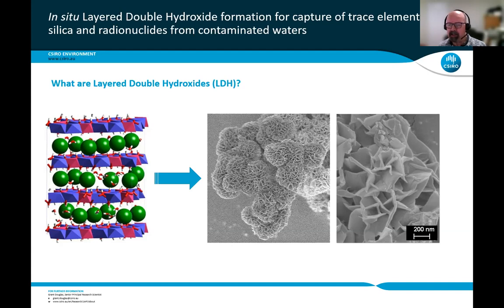Now, you've got a typical basal spacing in a layered double hydroxide between about 1 and 1.5 nanometers. So you're probably looking then at around about, say, 15 to 20 layers thick in that layered double hydroxide that we've got there. So just a little bit of an insight of what they actually look like once we form them.